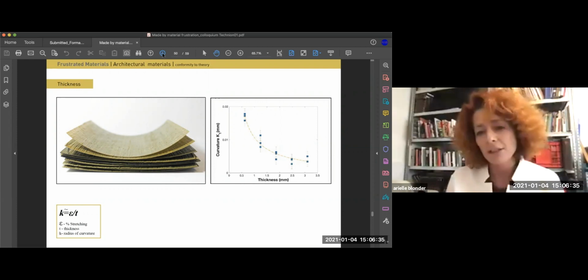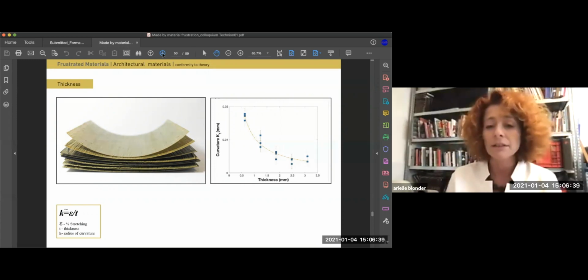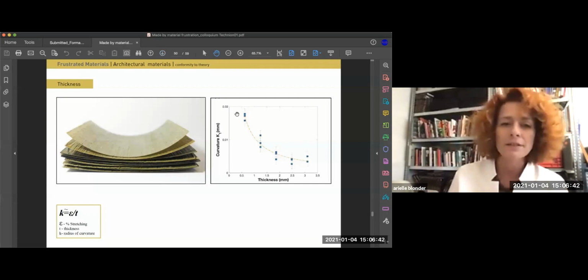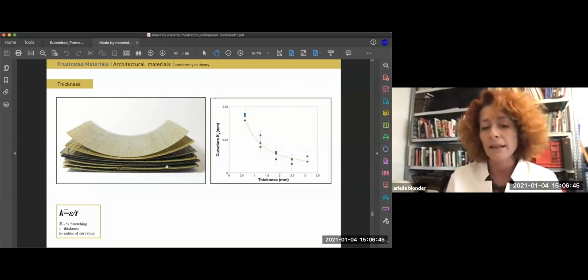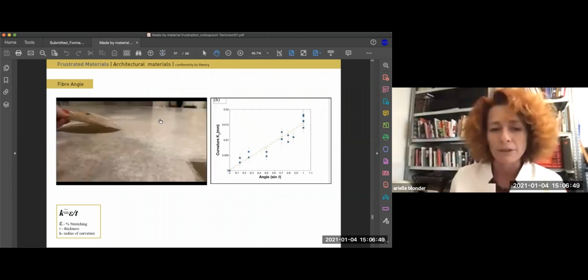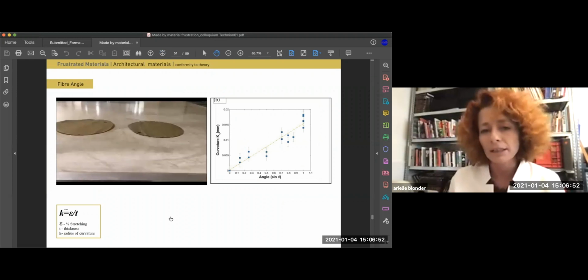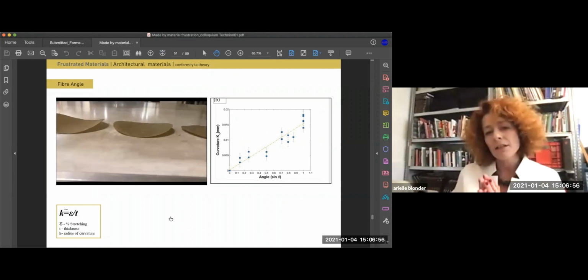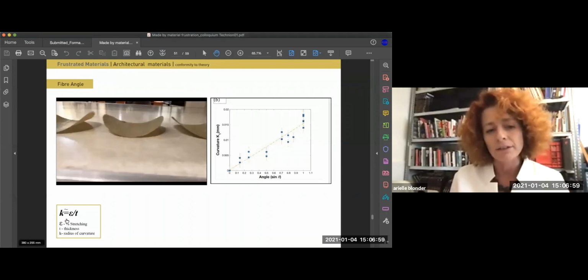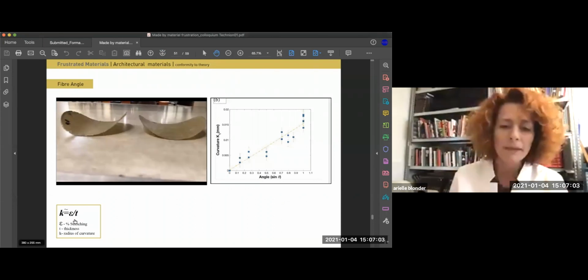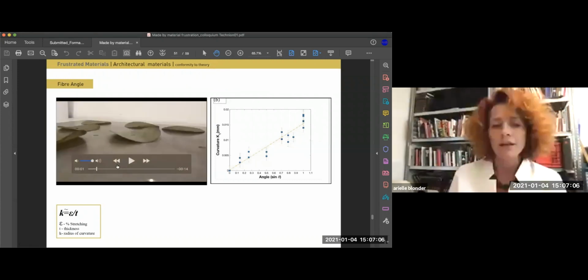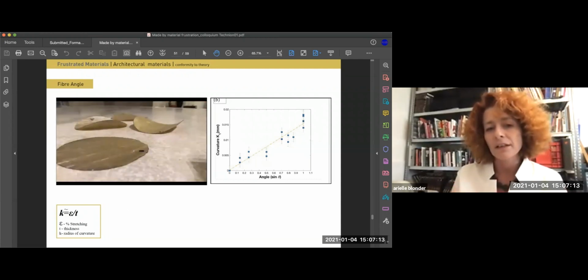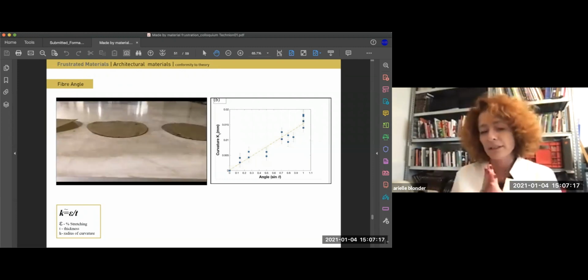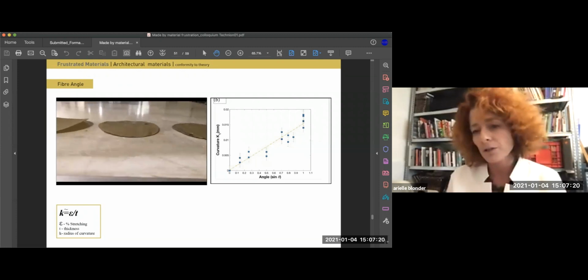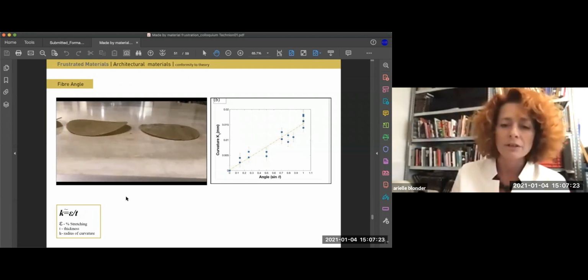But eventually we get very good results showing that when we increase the thickness of the material, curvature would decrease. So the radius of curvature would grow. Second element, and if you remember, these are the elements that we were testing initially in the latex tiles, would be changing the epsilon, or the amount of stretching of the material. And that is by different fiber angle between the layers. So you can see here, each disc would have a different radius of curvature according to the orientation of its two layers. And this also goes according to theory. The yellow bar is the theoretical line that this should adjust to.